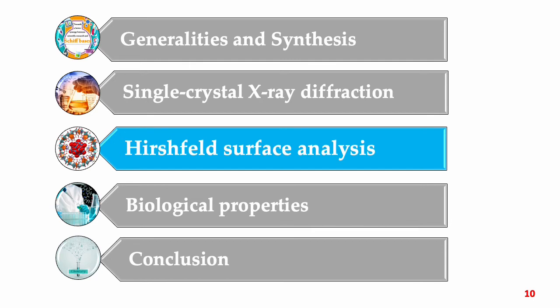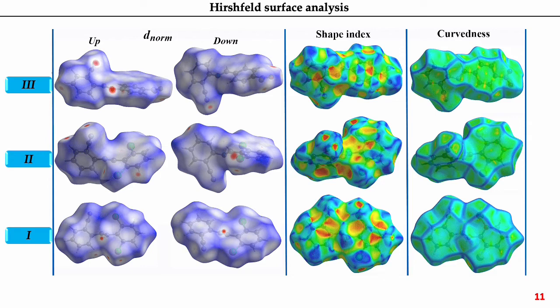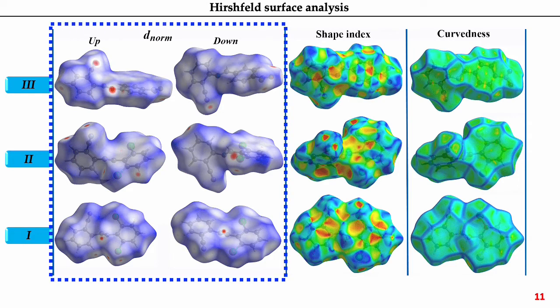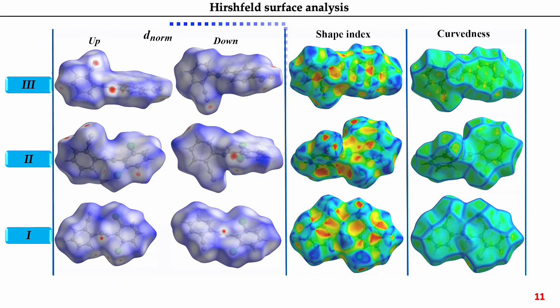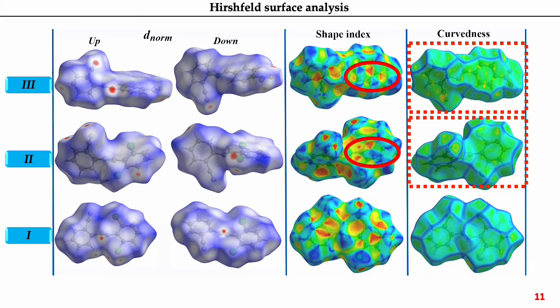The third part of our work is the study of intermolecular interactions by Hirschfeld surface analysis. The Hirschfeld surface was used to quantify the various intermolecular interactions in the 3 compounds. The view of the Hirschfeld surface mapped over d_norm shows white surfaces indicating contacts with distance equal to the sum of van der Waals radii, and the red and blue colors indicate distances shorter or longer than the van der Waals radii, respectively. A map of the shape index showing red and blue triangles indicates the presence of intermolecular pi-pi interaction in compounds 2 and 3. This is also evident from the presence of flat regions mapped over curvedness.